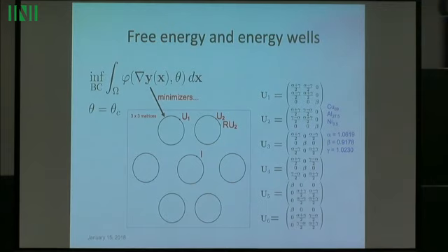In any case, the way you have to picture this phi is you fix the temperature. So I'm at the transformation temperature now, and you imagine a phi axis coming out at you like this, and the energy surface is a function of deformation gradient. So deformation gradient is a 3x3 matrix. So this square is all 3x3 matrices. And there's this phi axis coming out, and the temperature is fixed. And now this energy surface, its minima, comes down and touches the screen at some circles. This is at the transformation temperature. First of all, it touches the screen at the identity. The identity is a minimizer of phi at theta c.